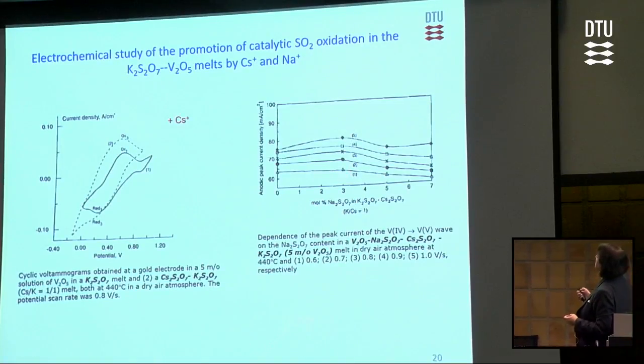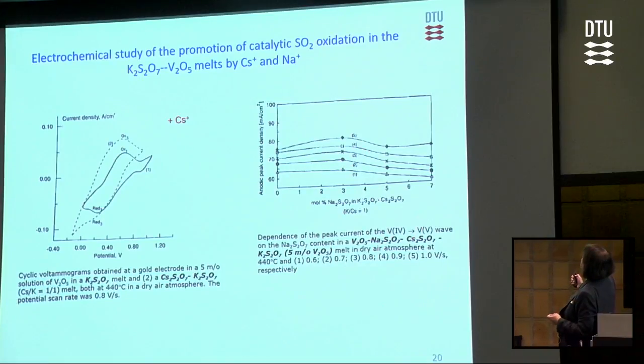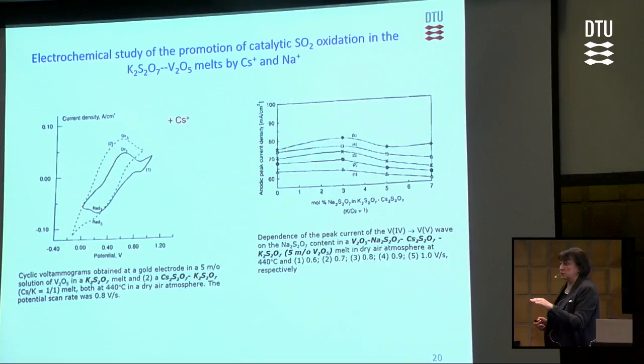Then we started a system with sodium and cesium, and we defined it on the background. So cesium is in a mixture like 1:1 with potassium, and then we add a little bit of sodium. We have found that on these backgrounds, cesium and potassium, the optimum concentration will be around here. If you look at the industrial catalyst, it will be exactly there.